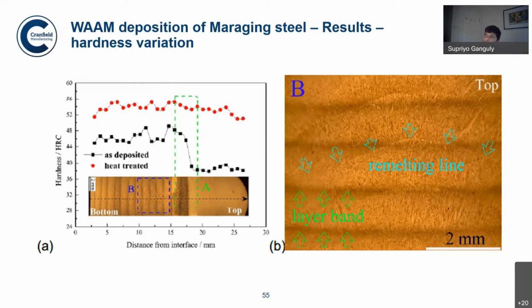When we take this whole structure and do the actual heat treatment, which is solutionizing and aging, the hardness jumps back to roughly where it should be. However, I will show you that it is still not enough, because the solutionization process is quite incomplete, and therefore this type of deposit will never achieve its optimum strength without some kind of mechanical working while depositing.